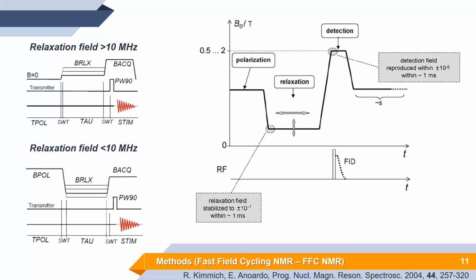So very briefly, because we already have heard about the field cycling and we are all experts in that field, this is a basic picture which shows the idea behind the method. The key information here is that field cycling allows us to run NMR experiments as a function of magnetic field strength at which the relaxation process takes place, in contrast to standard NMR spectroscopy where we use superconducting magnets at one fixed magnetic field. Depending on the magnetic field strength, we use different pulse sequences just to increase the sensitivity and the signal-to-noise ratio of our system.